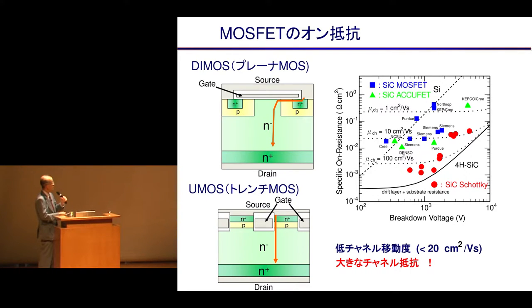There's breakdown voltage on the horizontal axis and specific on-resistance on the vertical axis, which shows the loss. With increased voltage, a unipolar device has high resistance. That's the limit for silicon. In the case of silicon carbide, as I said, there's about 2.5 times. And the MOSFET, well, ended up with a miserable result. Finally, we were able to exceed the limit of silicon, but we could not make further progress.